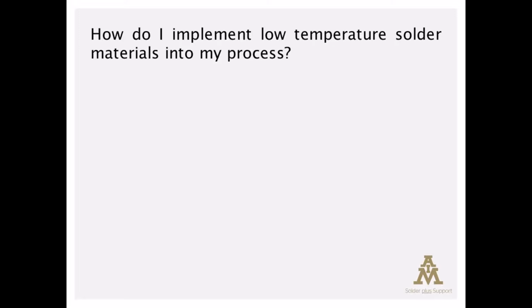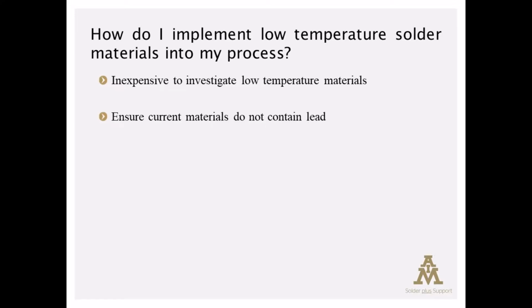Well, the good news is, Logan, that it probably shouldn't cost too much to at least experiment, and if you decide to go forward, to implement. The first thing that I would recommend is making sure that none of the materials that are currently in use contain lead. It's very important that a low temperature solder not make contact with lead, as a three-part alloy is formed with the bismuth and tin that has a melting temperature of 97°C, which causes a significant loss of reliability. So that's step one, and it shouldn't be a problem for most of the industry. There are still some legacies out there where we see tin lead in use, but they're becoming less and less common.